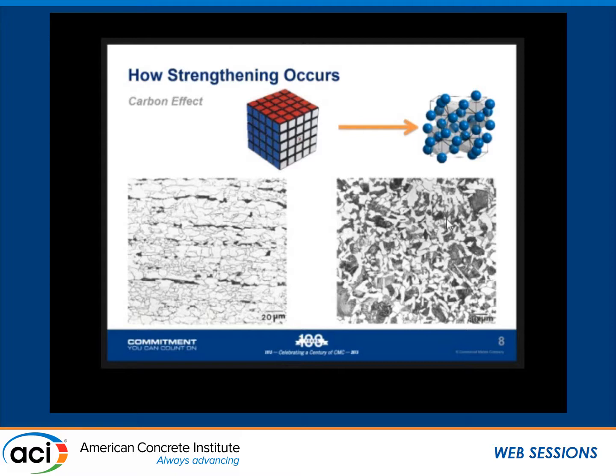If you look at this micro etch on the right, all the white areas are ferrite, which means they're a cubic arrangement. It means that those white areas of the steel can adapt to force. When you look over here and you see where there's a much higher carbon addition, the carbon additions are that black area, and it looks like this. So in this steel, only the white areas can adapt to force. The black areas cannot adapt to force. This is why when we add carbon, we lose ductility in the steel. There's just fewer regions of the steel that can actually adapt.